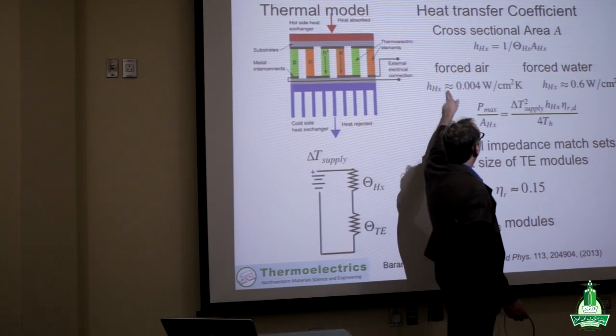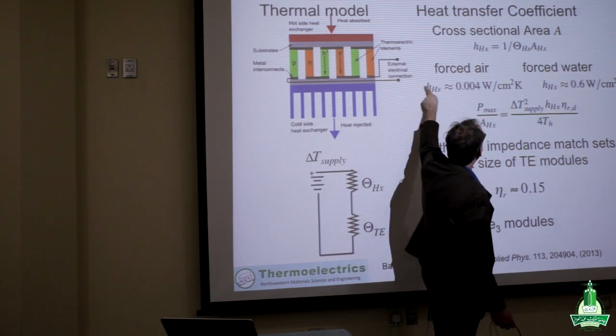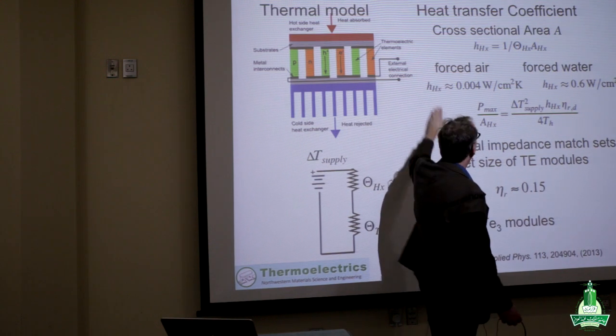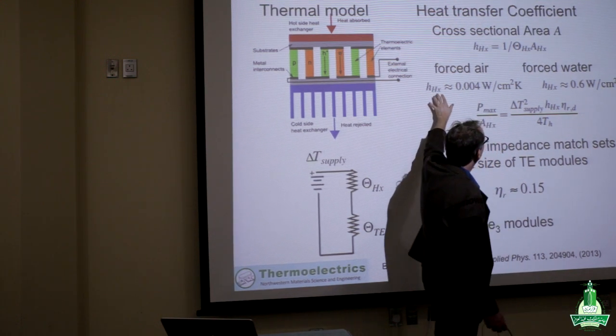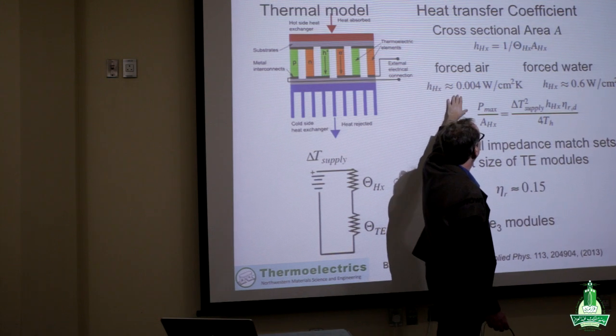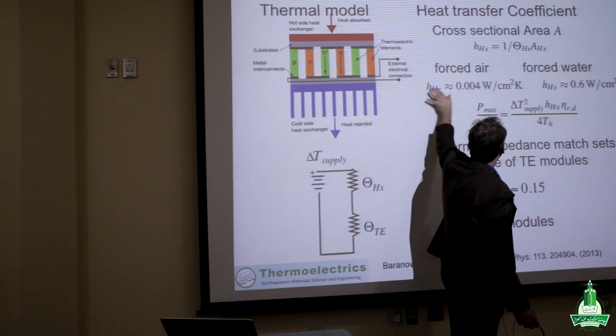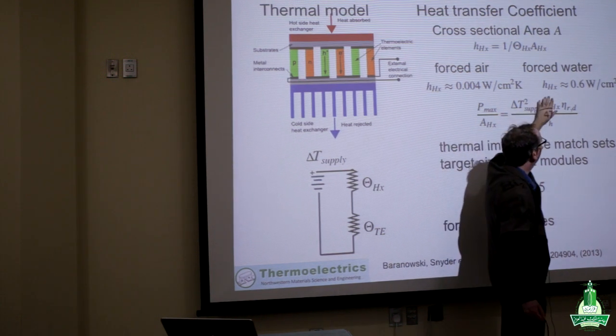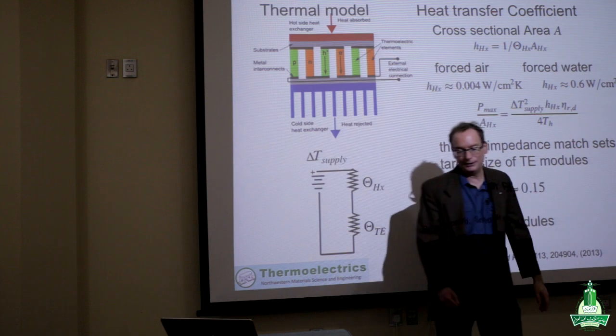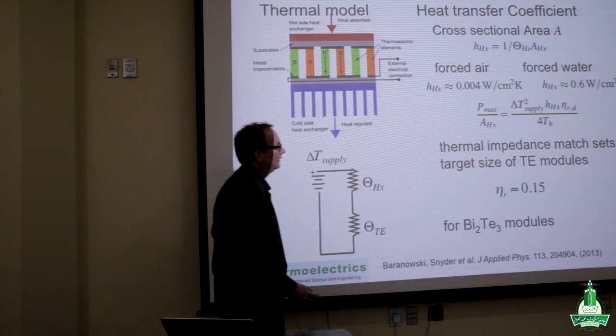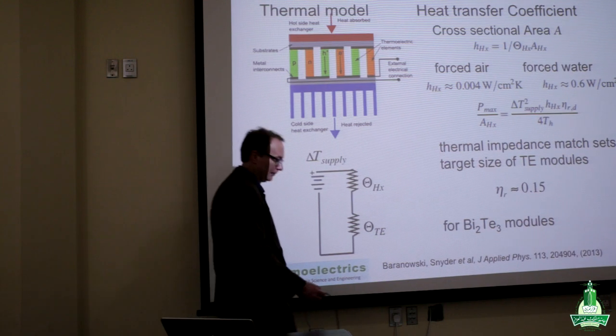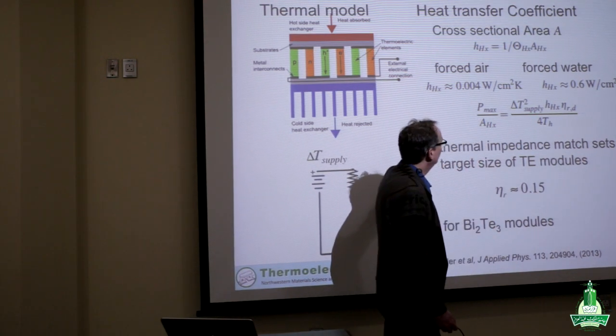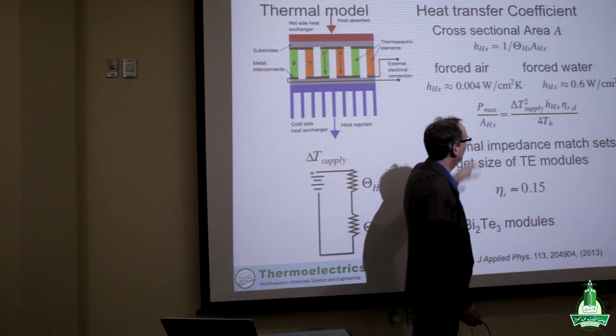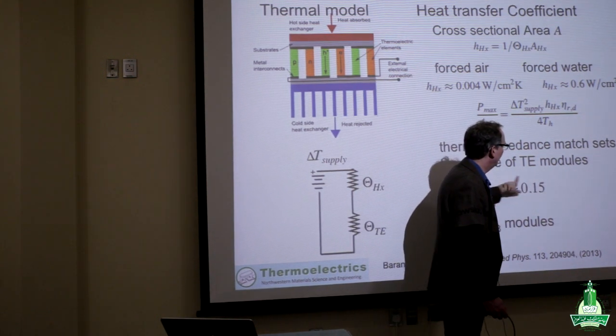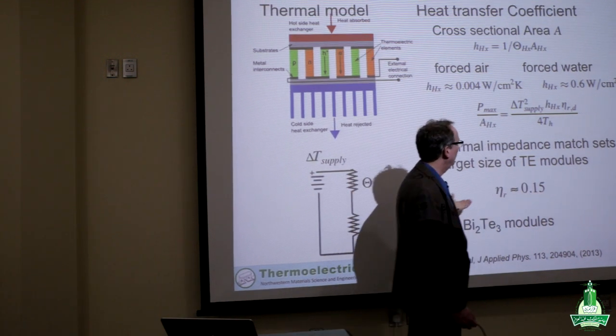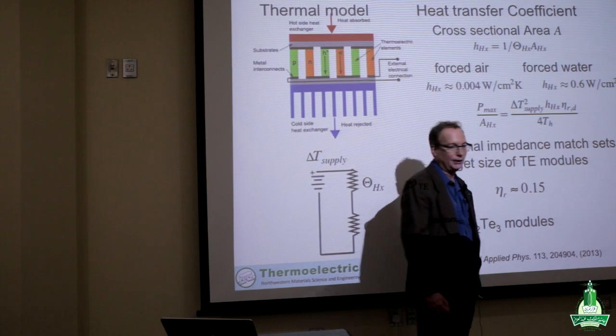And then, in order to get the most power, we are going to really have to be engineering that heat exchanger. And so those systems are typically limited by how we're going to do it. If it's a forced air heat exchanger, we get a relatively low value for heat exchange coefficient. And if we move to forced water, we might get a significantly higher one. But we have to make that system-wide decision. One can estimate the thermoelectric performance simply by using the relative efficiency relative to Carnot, which for a thermoelectric system is usually between 10 and 20%.